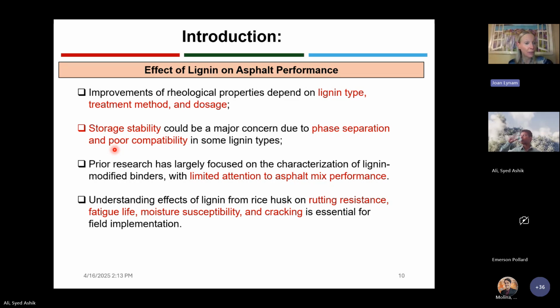So as some of these studies mention, storage stability can be a major concern. You can have phase separation after you've mixed in the binder. Some lignin types are going to have poor compatibility. There's mostly been lignin modified binder studies with just characterizing the binder, but there's been limited attention to asphalt mix performance, actually putting it in an asphalt mix. So we wanted to study the whole gamut, starting from how we got the lignin to what happened when it was in the binder to what happened when it was in the asphalt mix. So that was what we were excited about studying. So we can go on the next slide.